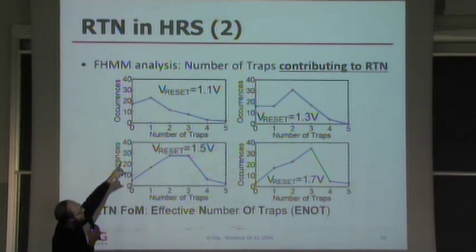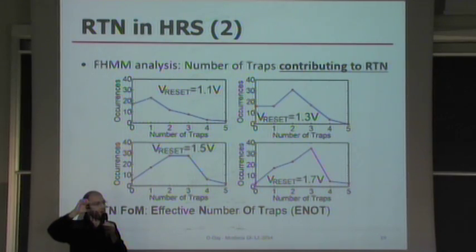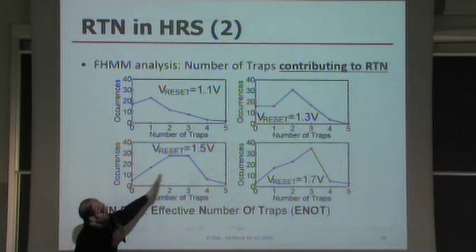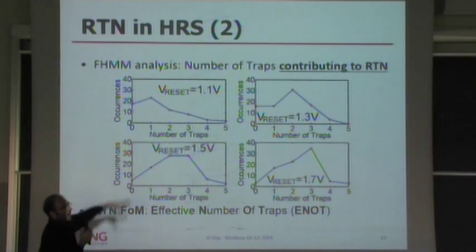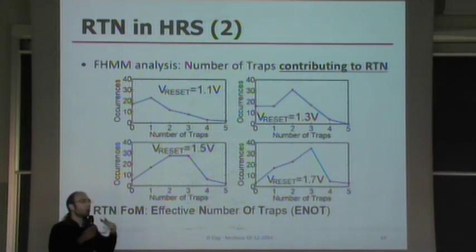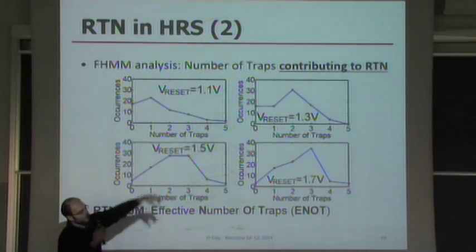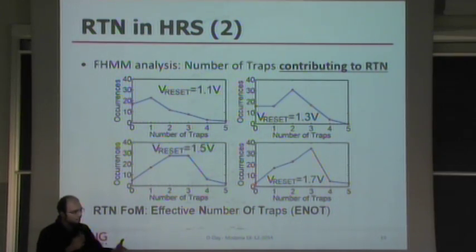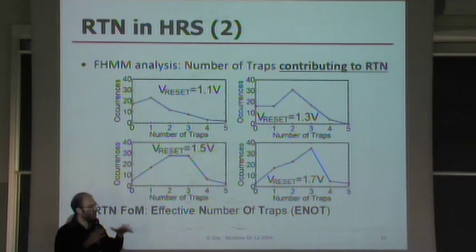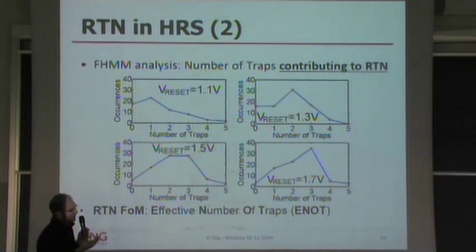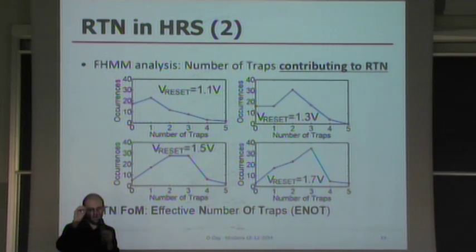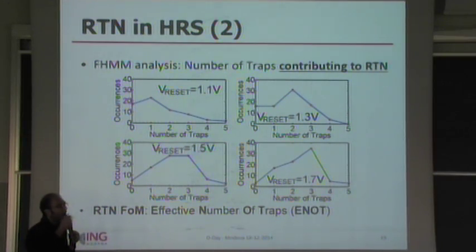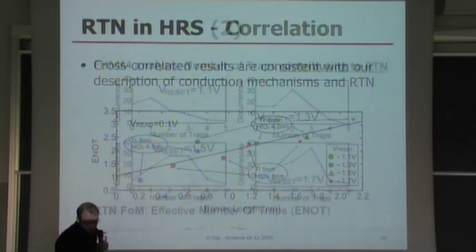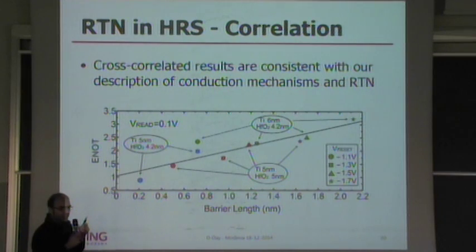But as you can see, if I move the reset condition, which gives a thicker and thicker barrier, this distribution moves. And if I take as a statistical indicator of the complexity of noise the integral mean of these curves, I obtain a number which refers to 100 switching cycles, and it tells me the average statistical complexity of noise. So we're going to use this value as an indicator of how complex this noise is. And that's a very intriguing result.